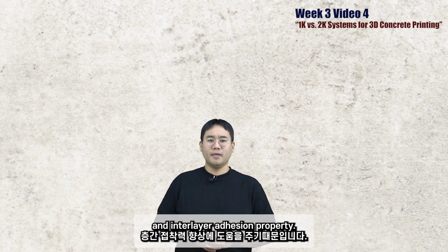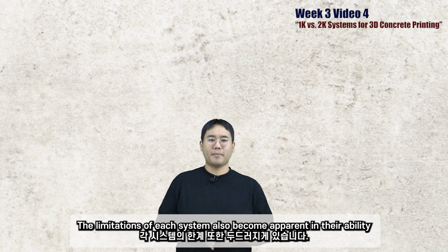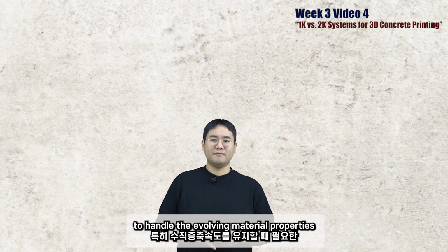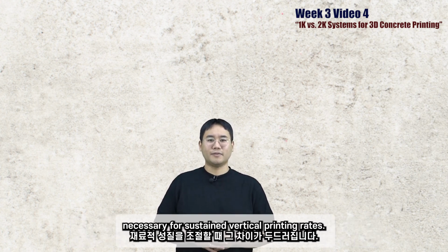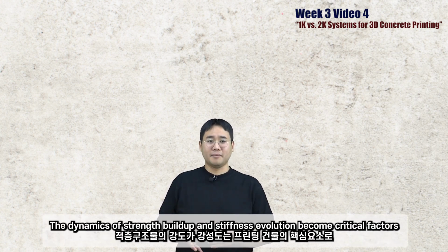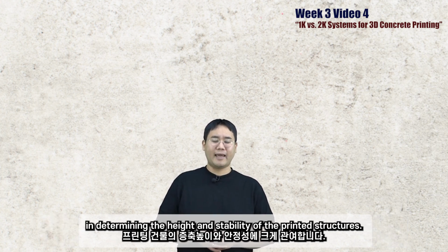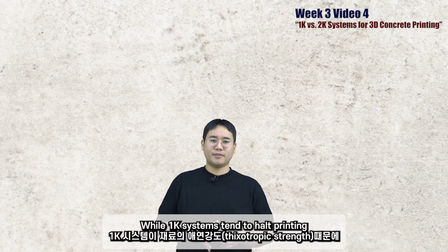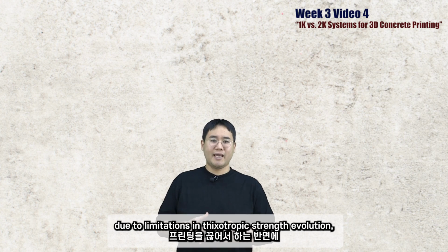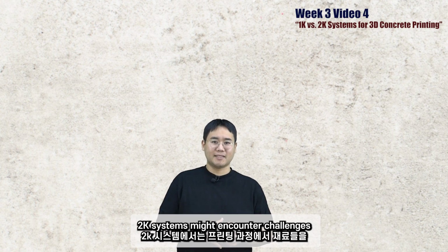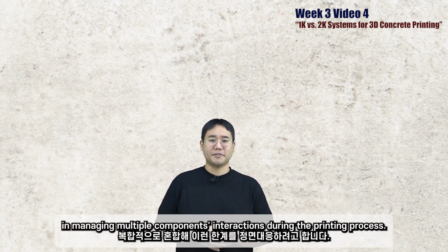The limitations of each system also become apparent in the ability to handle the evolving material properties necessary for sustained vertical printing rates. The dynamics of strength buildup and stiffness evolution become critical factors in determining the height and stability of the printed structures. While 1K systems tend to halt printing due to limitations in the thixotropic strength evolution of the material, 2K systems might encounter challenges in managing multiple component interactions during the printing process.